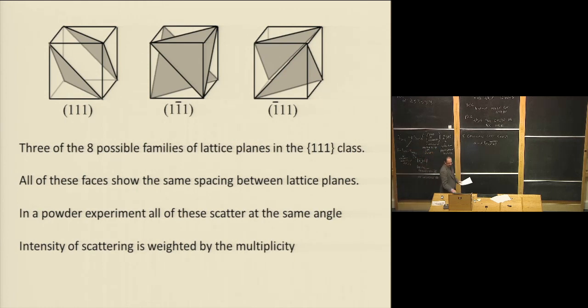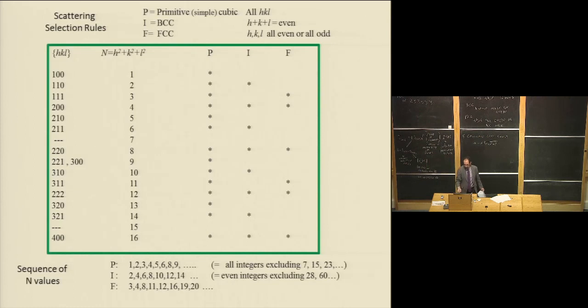So if we go back to this table here, add the multiplicities onto this table. If we're thinking about the 1-0-0 Miller indices, there's 6 possible directions which would present the same lattice plane spacing as 1-0-0, the 6 possible axes of the cube. But if we're looking at the 1-1-0, there would be 12 different ways you could face the cube that you would present the same lattice plane spacing. And someone won a chocolate bar for realizing that 3-2-1 has a multiplicity of 48.